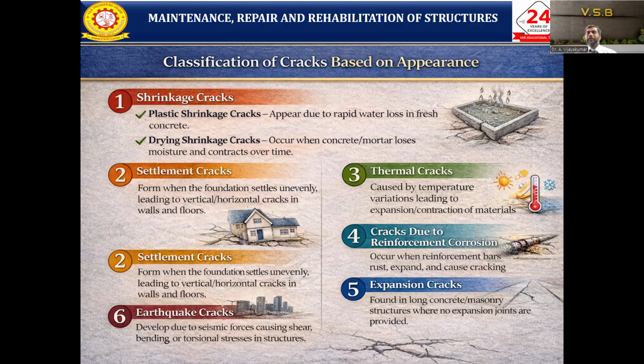Thermal cracks are caused by temperature variation, leading to the expansion and contraction of the material. Cracks also come when reinforcement bar rusts. Somehow moisture can enter the concrete surfaces, and the reinforcement rusts. Because of rust, expansion will come, which may be a cause of cracking. Take a long concrete or masonry structure where no expansion joints are provided: during the summer season it will expand, then during the winter it will contract. If the construction joint is not provided properly, what will happen? The members start to expand, and if no joint is provided, cracks will automatically start.